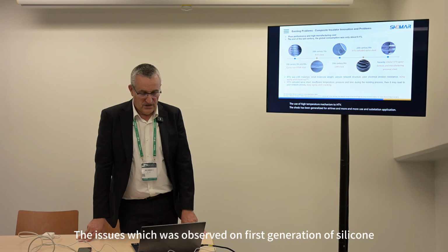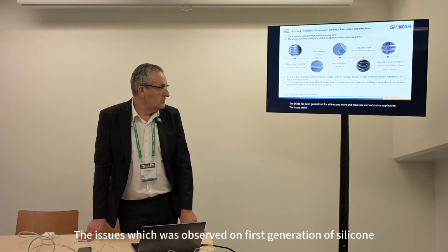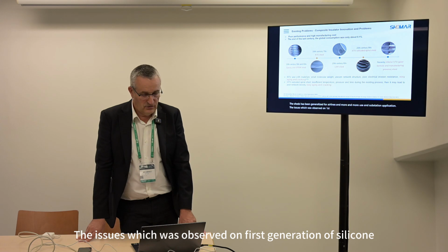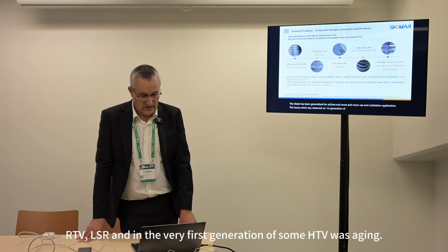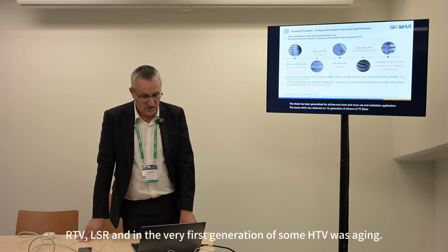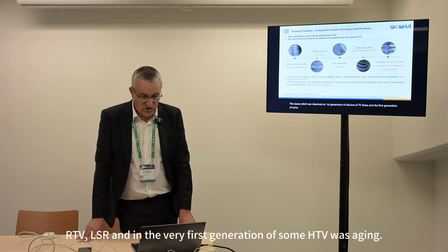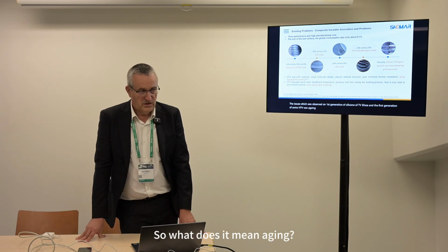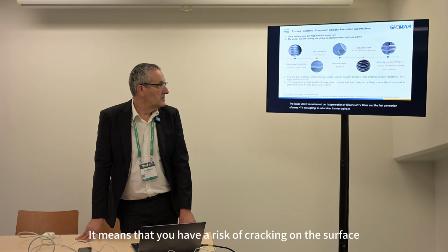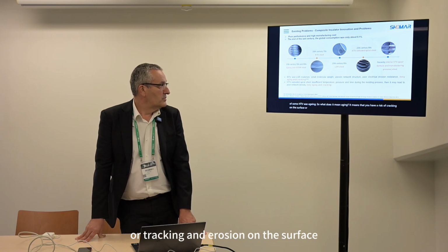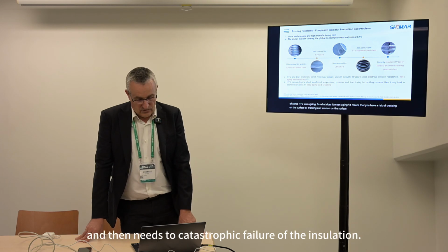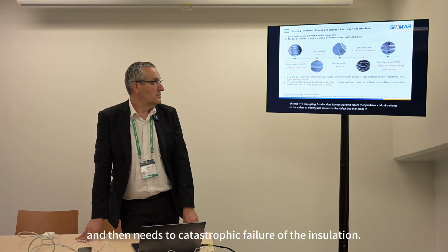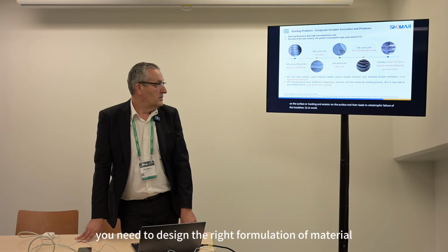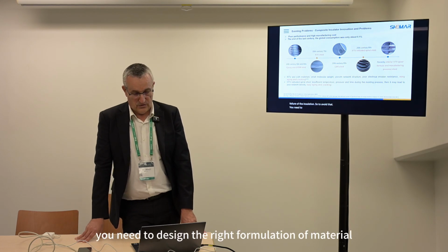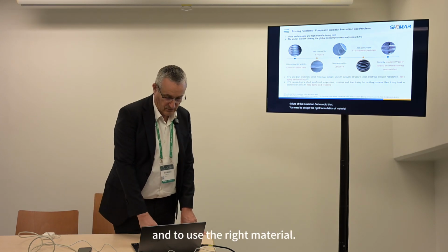The issue which was observed on the first generation of silicone, RTV, LSR, and the first generation of some HTV was aging. So what does it mean, aging? It means that you have a risk of cracking and erosion on the surface, which then leads to catastrophic failure of the insulation. So to avoid that, you need to design the right formulation of material and to use the right material.